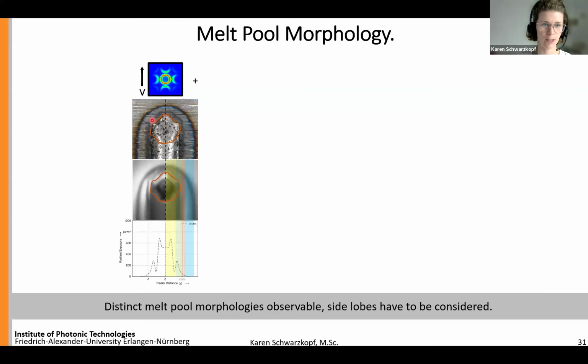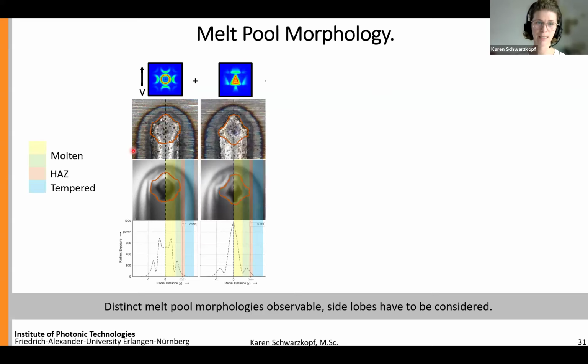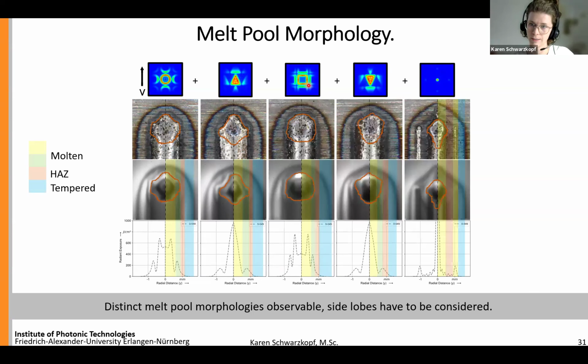We can see that it's not really incorporating a circular shape as we would expect from a ring, but we really see a dented shape coming from that beam shape here. And if we are now doing the same for the other beam shapes, we can again see that all parts of our intensity distribution are really mirrored in our melt pool morphology. This is the north-facing triangle, and also the same for the other three beam profiles. What is really interesting to see as well is the point profile, because here we can see not only one main melt pool, but also smaller side lobe melt pools that are correlating with the position of those side lobes. So this means that here the intensity is high enough to also melt our material.